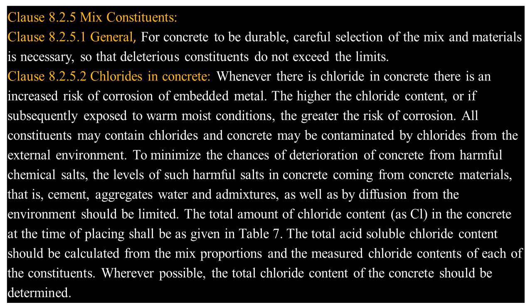Clause 8.2.5.2 Chlorides in concrete. Whenever there is chloride in concrete there is an increased risk of corrosion of embedded metal. The higher the chloride content, or if subsequently exposed to warm moist conditions, the greater the risk of corrosion. All constituents may contain chlorides and concrete may be contaminated by chlorides from the external environment. To minimize the chances of deterioration of concrete from harmful chemical salts, the levels of such harmful salts in concrete coming from concrete materials, that is, cement, aggregates, water and admixtures, as well as by diffusion from the environment should